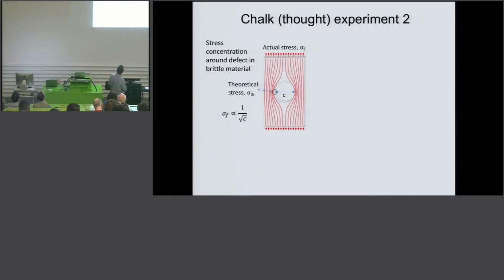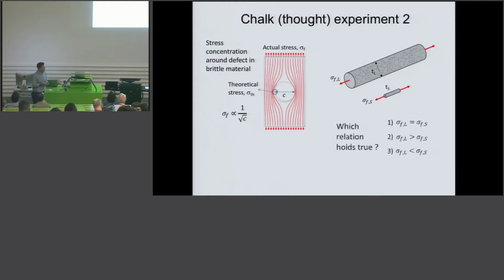And what's even more interesting is that people figured out a very simple correlation between the fracture strength of such a brittle material and the size of its defects. So it scales with 1 over the square root of the defect size. So now we go for our experiment. I have this big piece of chalk and I have a small one. Which relation holds true? First, the strength of this big one is the same as the small one. The large one is stronger, or the large one is weaker.